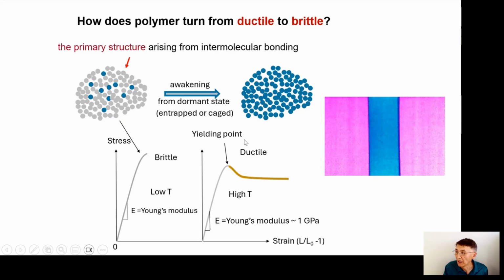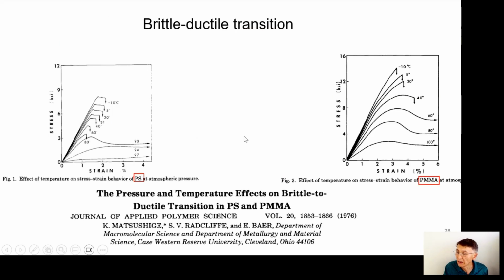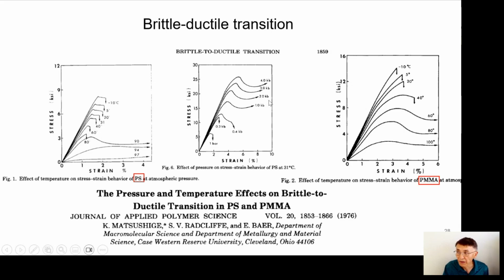So coming back to why a polymer is ductile, it is about why the monomers can become activated. That process determines whether ductility occurs or not. This is just some old data showing that if you have polystyrene or PMMA, high temperature is ductile. As you go through cooling, it turns brittle. For example, at 50 degrees, PMMA is about to change from brittle to ductile. And this old paper discovered that if you pressurize your polymer, it can turn from brittle to ductile at room temperature.